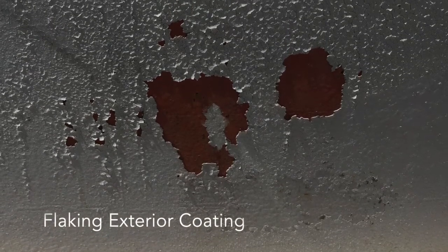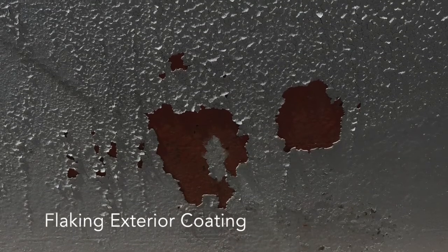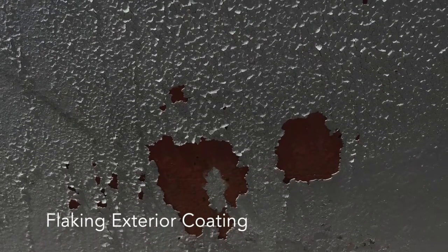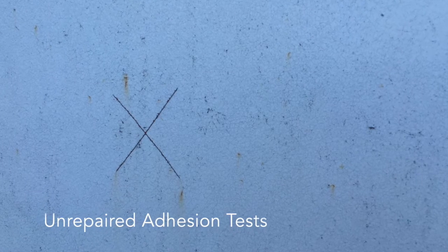The exterior coating began to break down, crack, and peel off quickly with exposure to sunlight and the elements. Also, it is possible that too much solvent was added when the coating was applied, and being very thin with poor surface preparation resulted in a short coating service life.